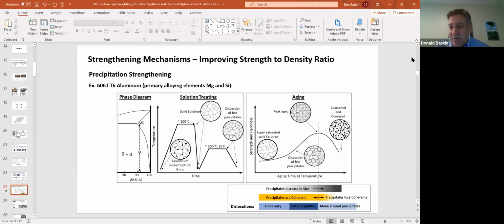So there's a point where these dislocations, when they're small, are most effective at stopping dislocation motion, or making it require more energy to move a dislocation through the matrix. When they're small, the atomic planes and lattices of the precipitate line up with the material around it. We call this a coherent precipitate.